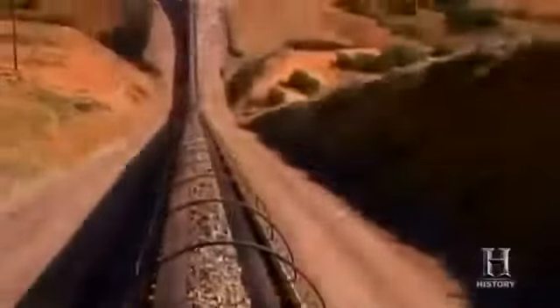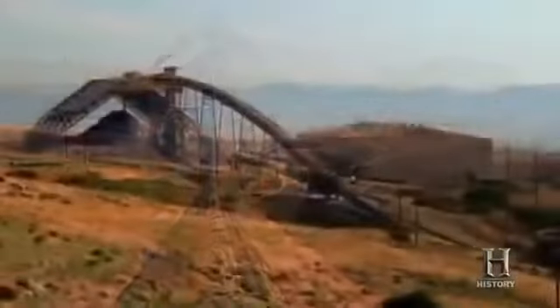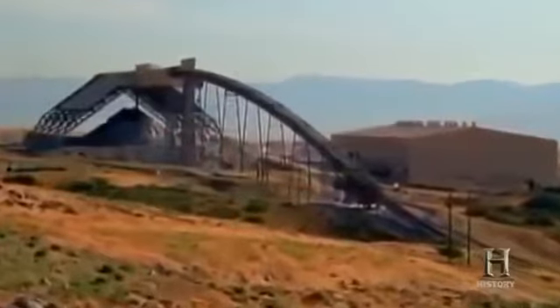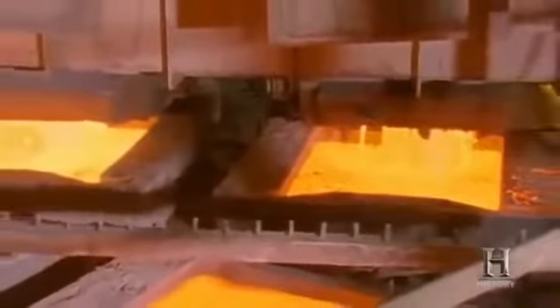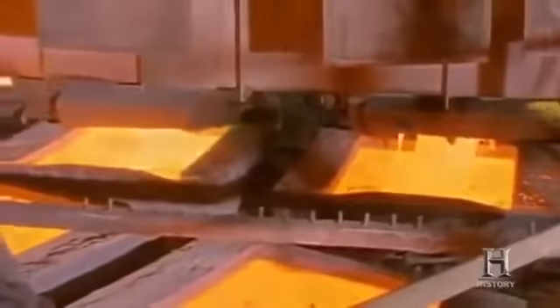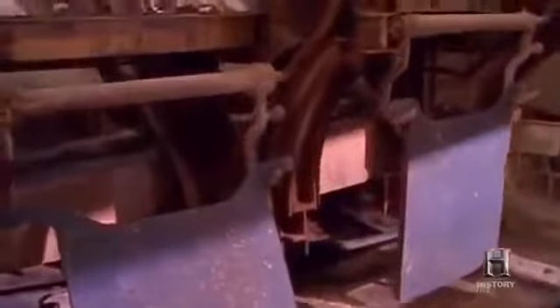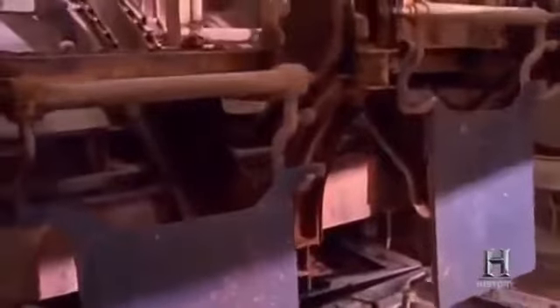After the rock is blasted free and crushed, a series of conveyor belts carries it 5 miles to the concentrator. There, flotation cells separate out a liquid that's 28% copper. The liquid is pumped 17 miles to a smelter, where furnaces refine it to 99.6% purity, and it's cast into 700-pound plates called anodes. But 99.6% is not pure enough.